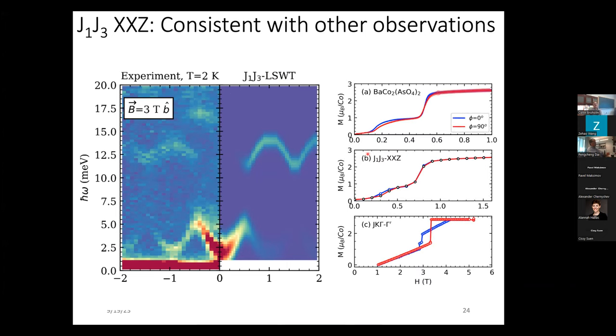The other thing that turned out to be quite a good indicator is we're showing here the magnetization measurement for 2 different field directions. So these are in-plane field directions, rotating either along the A direction or along the perpendicular B star direction. So 2 perpendicular directions in the plane, either along the nearest neighbor bond direction, or along the third near neighbor bond direction. And it turns out that the material is not very anisotropic. And here you can see once I get above about 0.55 tesla, then I'm almost completely saturated in the magnetization, almost completely ferromagnetic in the plane.